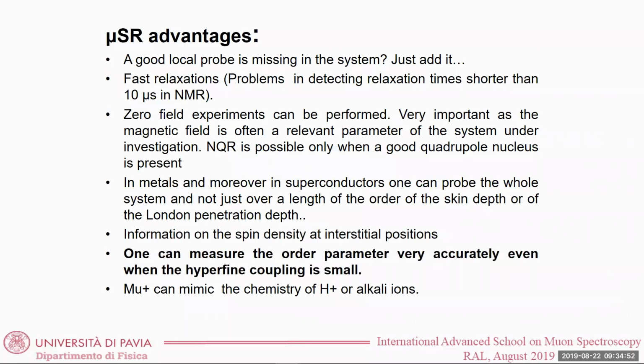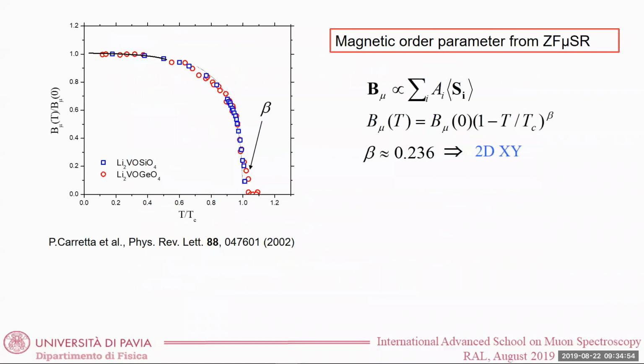When is μSR still relevant? Well, if you want to study in zero field, without perturbing our system, the magnetic order parameter. This is, for example, in the case of an antiferromagnet, where we can study well the critical exponents. We can study, for example, the reduction of the magnetization at low temperature. This is just zero field μSR in these two systems. This is the temperature dependence of the local field at the muons that you can study. And you can study well this order parameter.